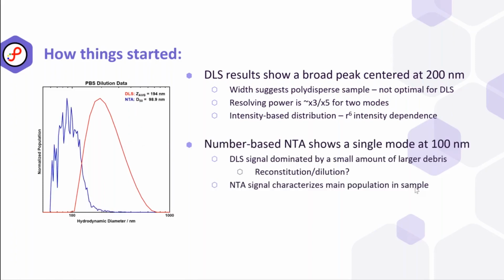If we look at an NTA result for this, we see a completely different story. We see a single mode that's roughly centered around 100 nanometers. And this is likely because the NTA technique, especially with the blue laser available, is capable of measuring the smallest particles that are present down to about 50 nanometers. And that's what we're really seeing. So that's the dominant population in our suspension.